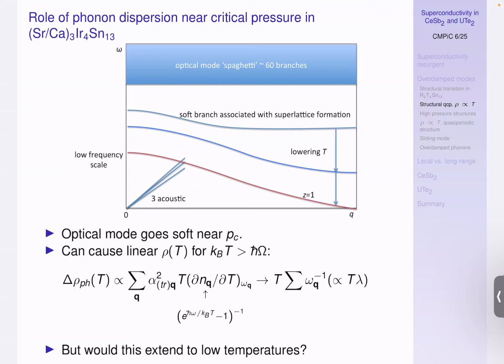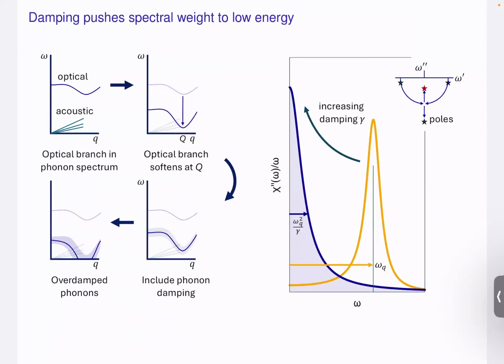The idea is that it's because we have a soft phonon branch. But I was never really personally convinced that this can be the full story, because it's difficult for me to believe that the dispersion of this branch really stays small enough. The frequency will go to 0 around here, but it should still have some significant dispersion. So I always found that a bit unconvincing as a full explanation. So I'm beginning to wonder, and it's difficult to prove, but I think it's a promising idea: what happens if we also add in the fact that phonons have a finite lifetime?